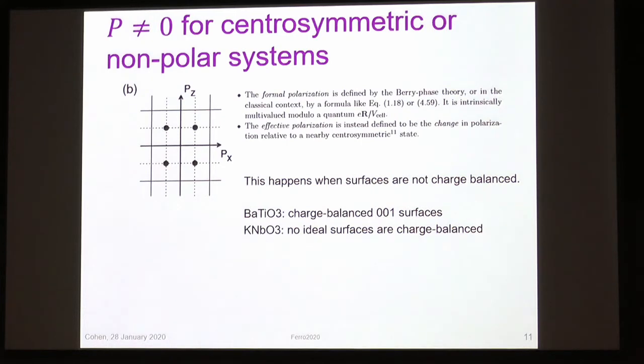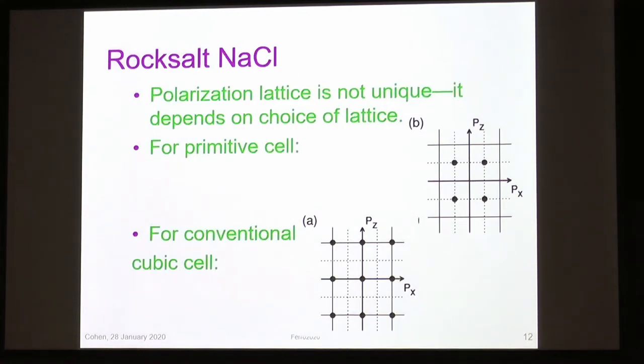So this is one of the issues that I have, because if you look at the thermodynamic theory, it says that the polarization is the derivative of the free energy with respect to electric field, and that does not allow P equals zero not to be the answer for the centrosymmetric case, right? And if you take rock salt, again, if you take two different cells, like I mentioned, you'll get two different types of lattices. So these are really inequivalent from each other. And so if you want to argue that one of them is correct and the other one is not correct, I think there's a problem. In fact, both of them are correct in a sense, as I'll point out.